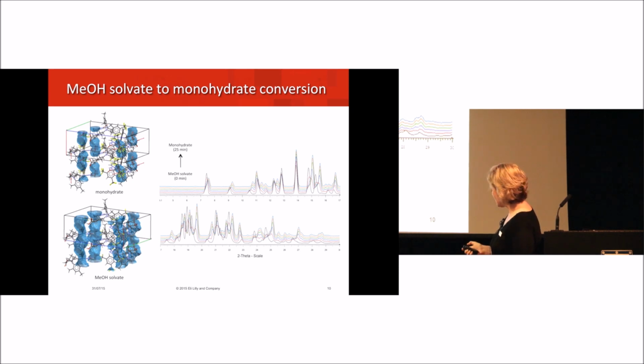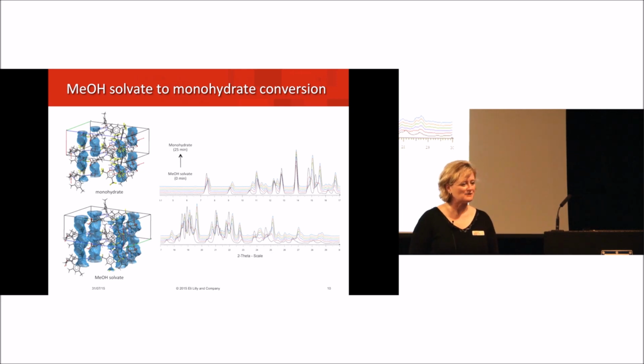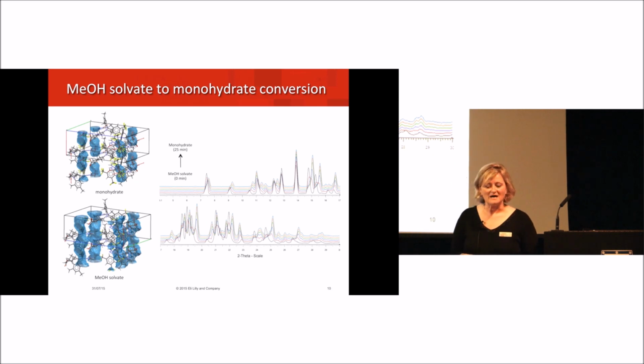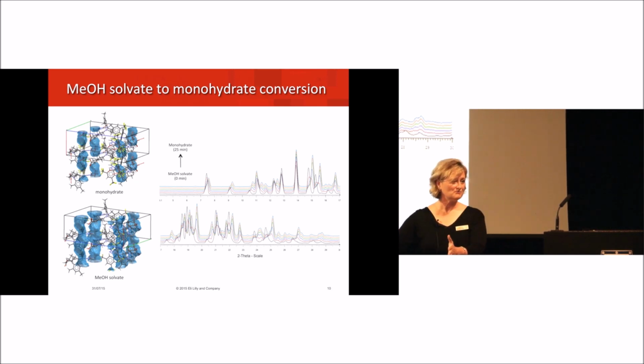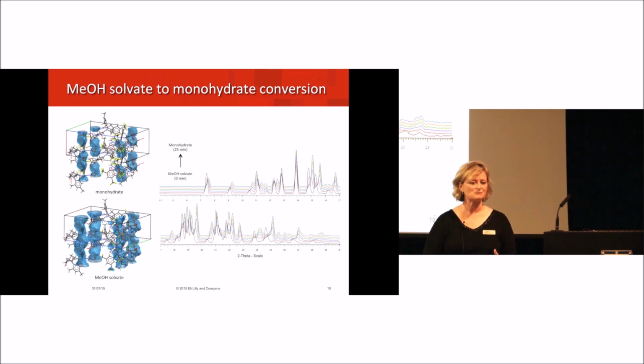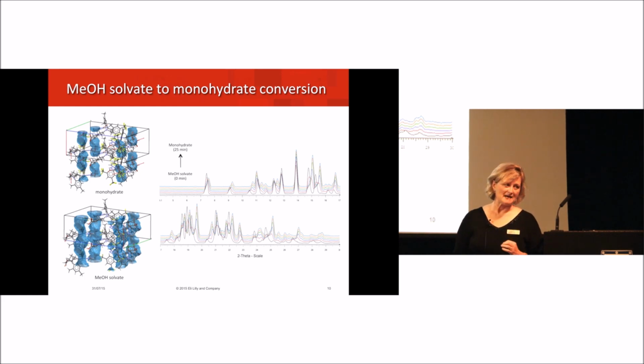This just shows what happens to the crystal structure that we initially crystallized, being a methanol solvate, and how we could rationalize the water coming into this solvent, and a slight decrease in the unit cell parameters to where we formed a reasonably stable monohydrate composition. Now, we were really happy. This actually represents a breakthrough when it comes to the development of our compounds, because now we have a purification pathway, we have a delivery and a stability pathway, all the benefits of the crystalline state. So we were exceptionally happy about this.